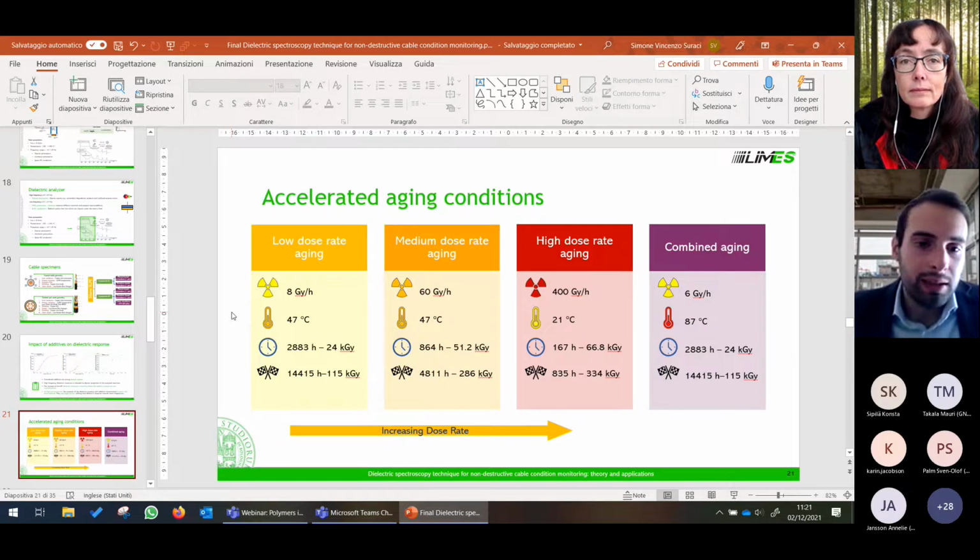In particular, the chemical analysis showed that no DLO was present inside the materials analyzed. So I would say that this aging is accelerated because of the very high doses, but it is not related to the DLO effect.